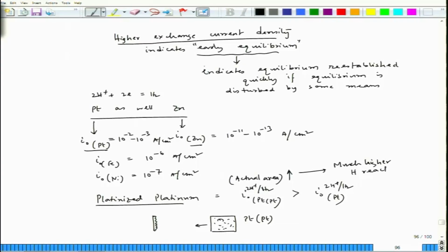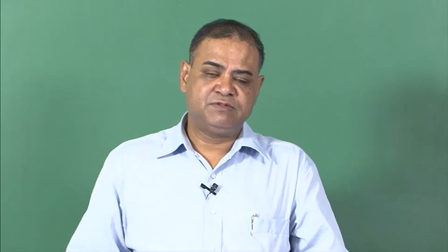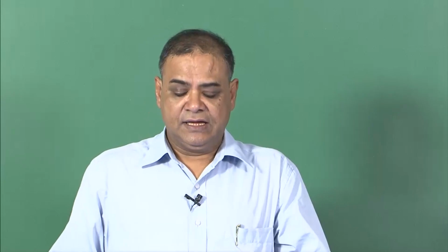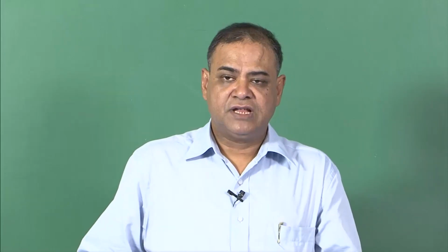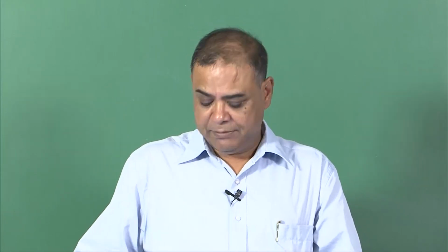which leads to much higher hydrogen reaction, or I0 increases. It suggests that if we use platinized platinum in place of platinum, the standard hydrogen electrode would be much better, because in case of platinized platinum, I0 is higher. So, the equilibrium would be much more stable, or if we disturb this, it will come back to the equilibrium quickly. So, that helps us to maintain the standard potential of that hydrogen electrode, so that we can measure the potential of another electrode with certainty.